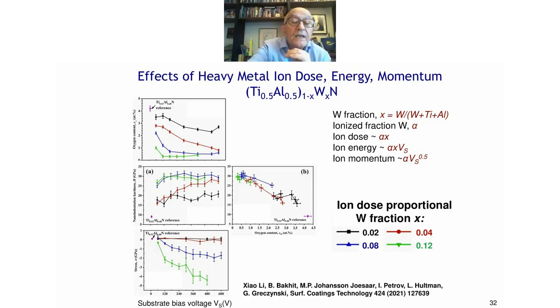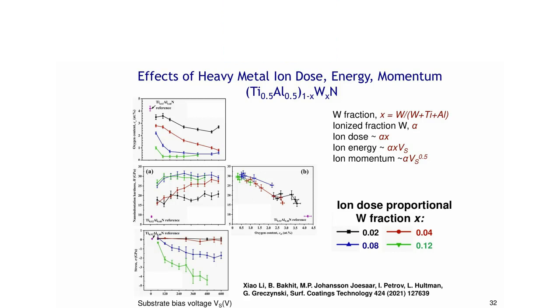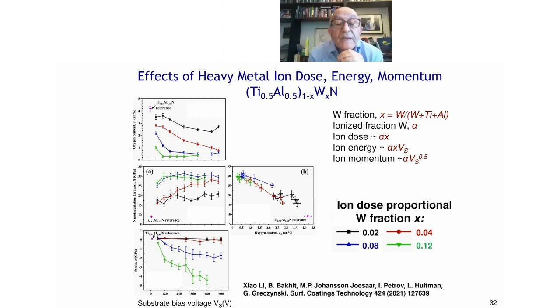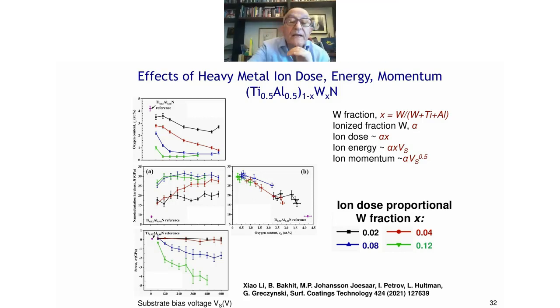And with that amount of tungsten, you never get high hardness. The panel to the right compares the oxygen content or density versus hardness. And you can see the density and hardness go hand in hand. So the dense films are hard, the porous films are soft.